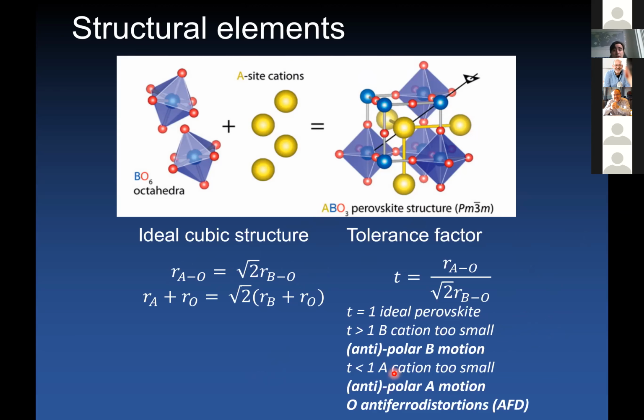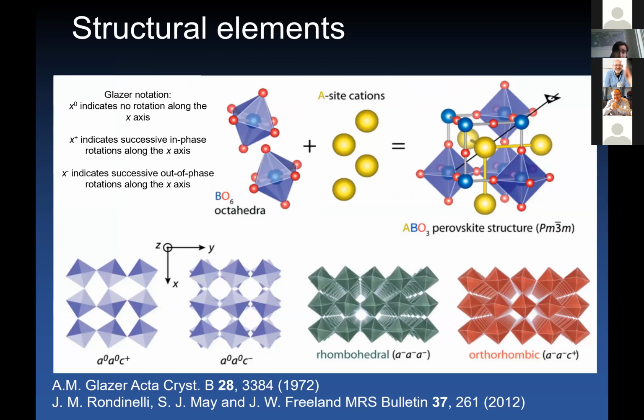If instead you put in a cation that is too small to realize the cubic symmetry, then the system has an instability to create antipolar or polar motion of the A atom this time. And this is also accompanied by oxygen octahedral rotations from antiferrodistortive modes. So the key aspect is that the perovskite system is very tolerant to accommodate many types of cations, with the price to pay of realizing various structural distortions.